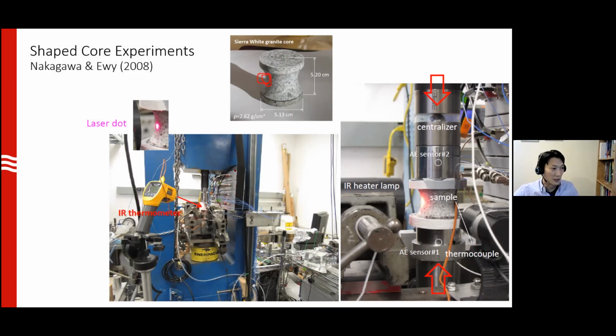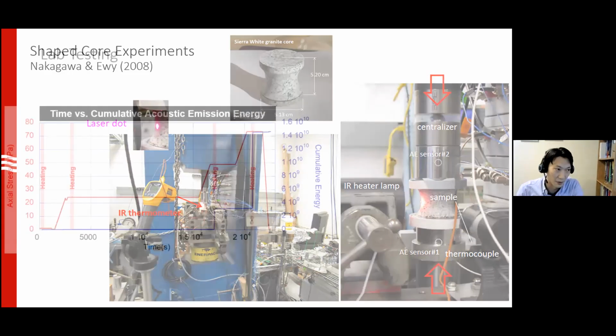They know that they can load the rock until failure forms to simulate a breakout. This was originally done by Nakagawa and Ewy at Chevron, where they were trying to simulate a breakout failure by loading the sample axially. What Seiji did is load until they put in some axial stress, but not enough to create the breakout, and then he spot heated the surface of the rock to simulate the thermal stress that we are trying to create in a borehole. He also has AE sensors embedded in the piston so they can monitor the activity.